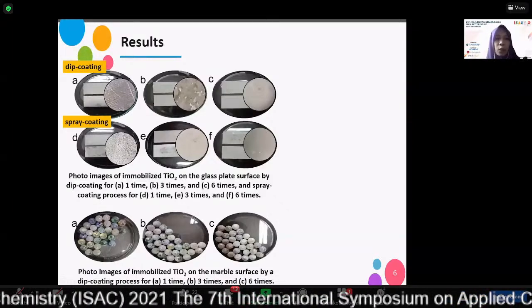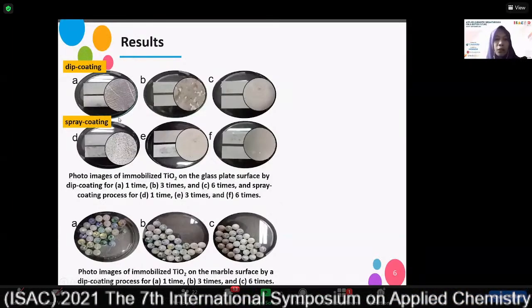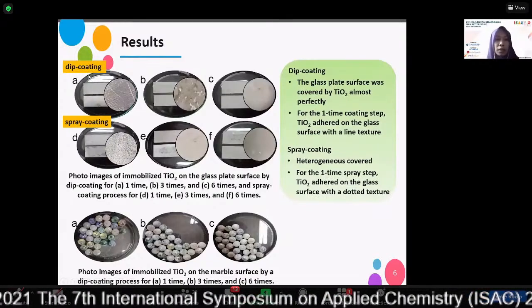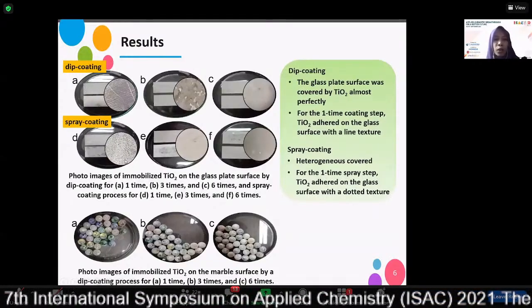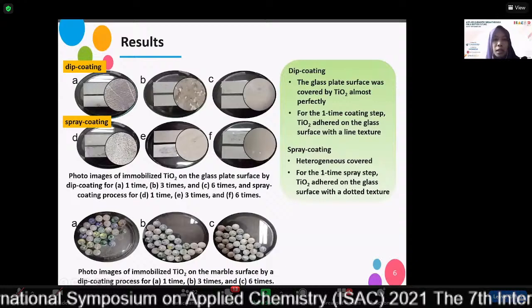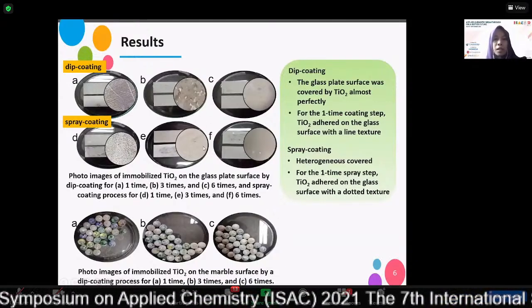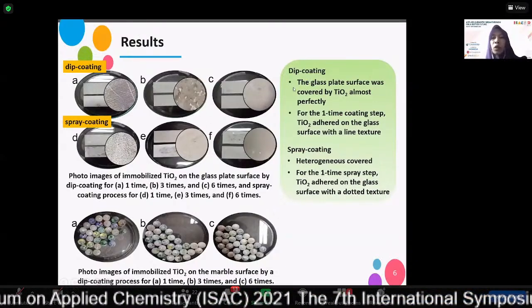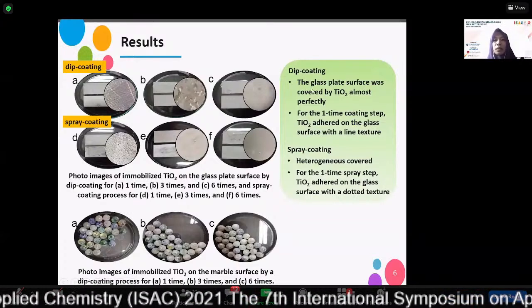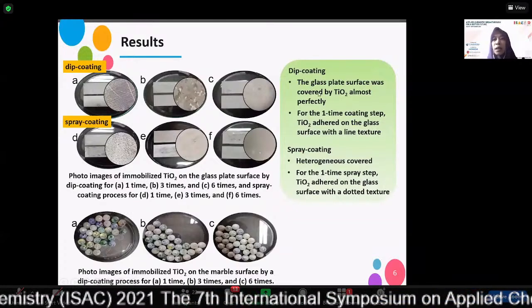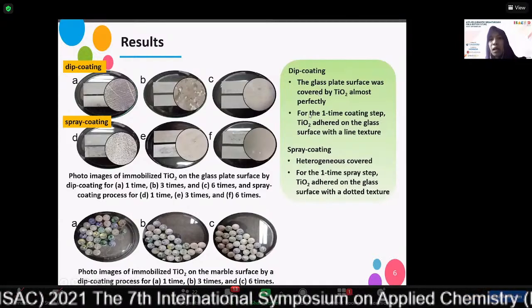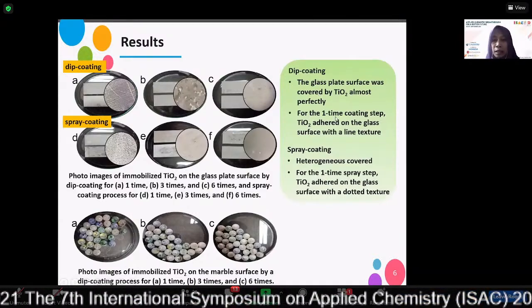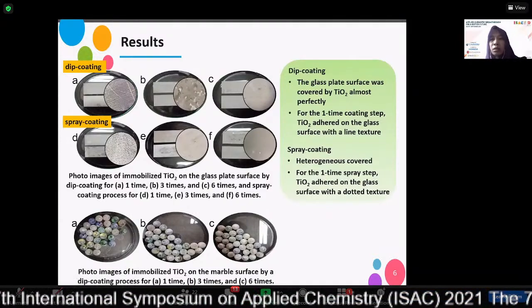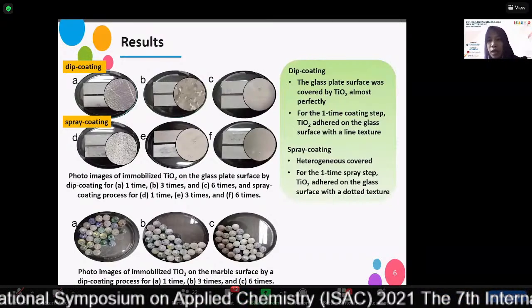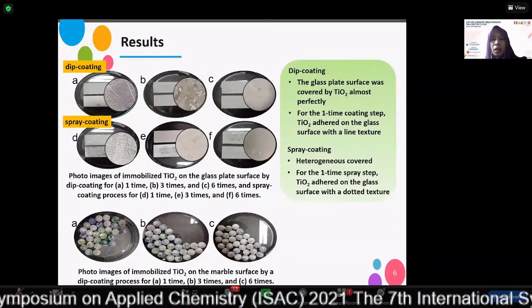This is the result of dip coating and spray coating. For A and D is 1 time, B and E is 3 times, and C and F is 6 times. For the dip coating, the glass plate surface was covered by TiO2 almost perfectly. And for the one-time coating step, TiO2 adhered on the glass surface with a line texture.